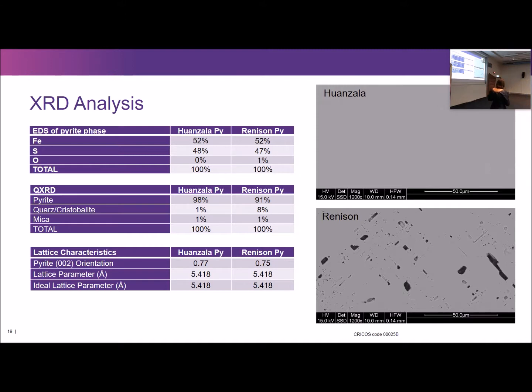So, when we did the EDS of the pyrite, they were both roughly 52% iron, very similar sulfur contents. Again, the Renison contained a little bit more oxygen, but otherwise they were chemically identical. I also assayed them. I didn't include the results here, but the results were also the same. They were chemically practically identical.